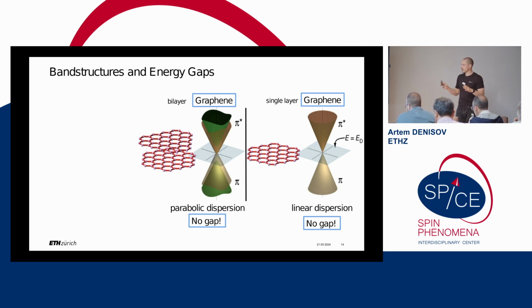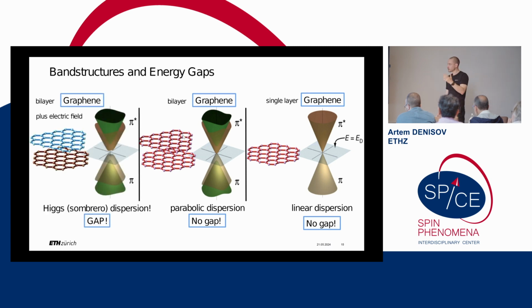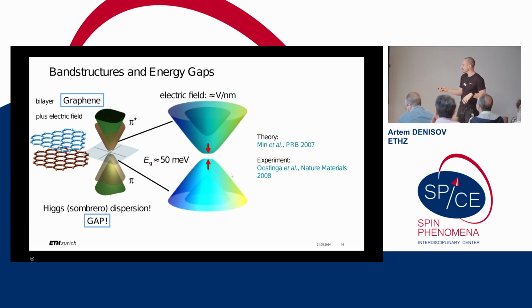If you don't apply any external electric field, it's a semi-metal too, with a bit different dispersion. Instead of linear dispersion close to the charge neutrality point, it has a parabolic dispersion. However, if you break inversion symmetry, if you apply an electric field, so if you shift your carrier wave function from one layer to another, you can actually open a gap in the spectrum. This phenomenon is like a textbook example of how breaking inversion symmetry can open a gap, and the spectrum is also known as a Higgs dispersion or Mexican hat dispersion because it looks like a hat, shown here. The size of the gap is controllable by the displacement field, so by how much voltage you can apply to the back and the top gate.